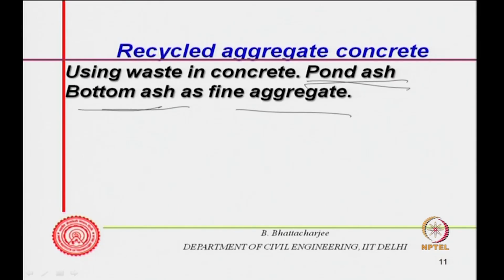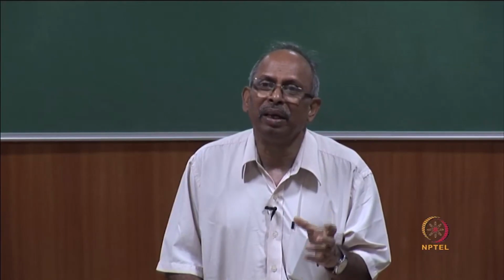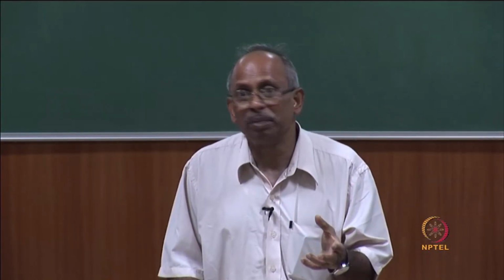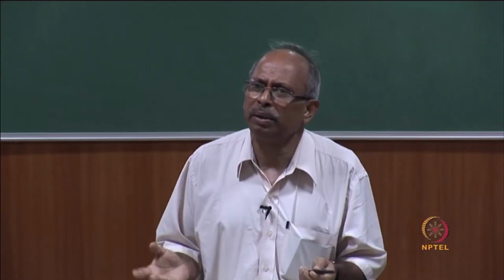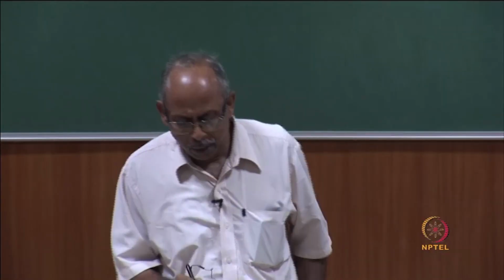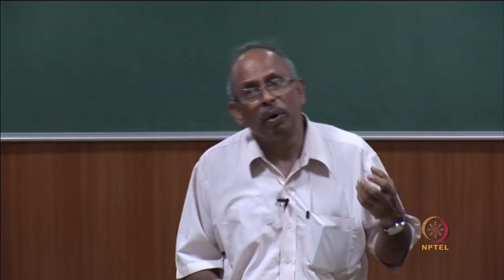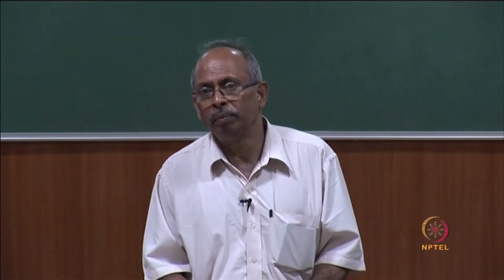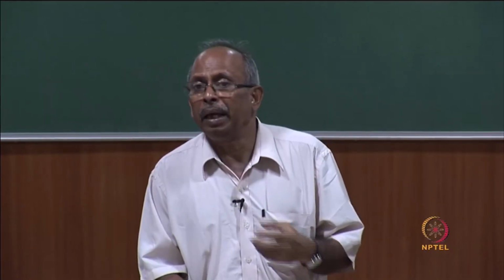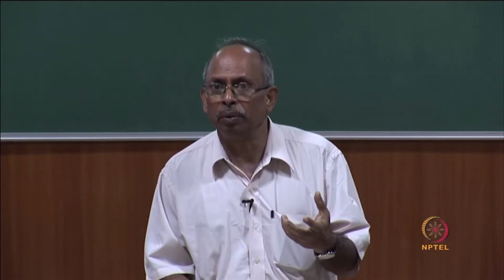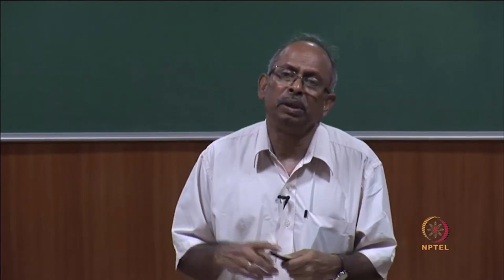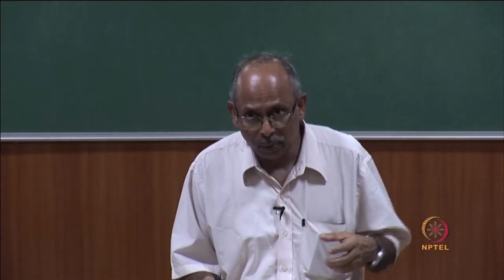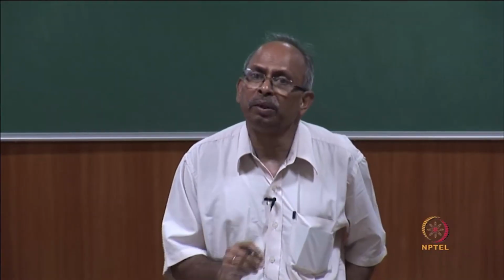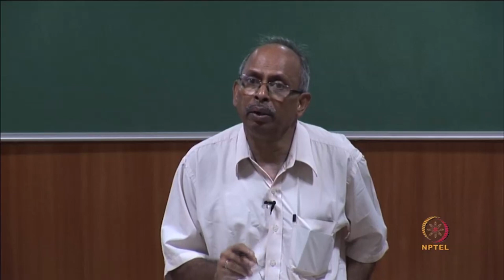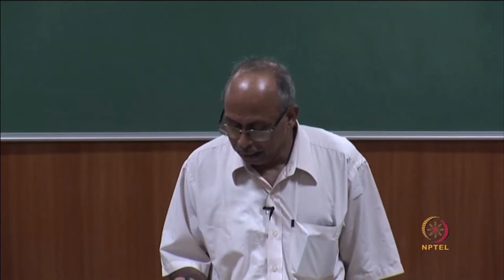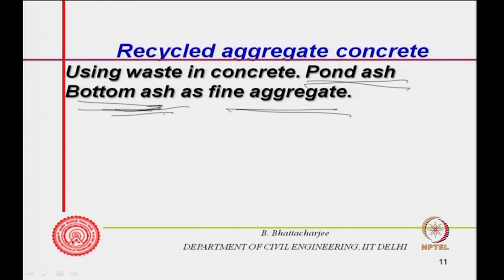But one must characterize this material and design this mix. Some, one can use them successfully, there is no problem. Bottom ash got another advantage. If you are collecting directly from the thermal power plant, they can actually give you good thermal insulation as well. However, these materials are to be seen and designed, because there are components of spherical particle there and hollow spherical particle, and generally their density is lower, but strength can be higher. So, therefore, pond ash or bottom ash as fine aggregate.